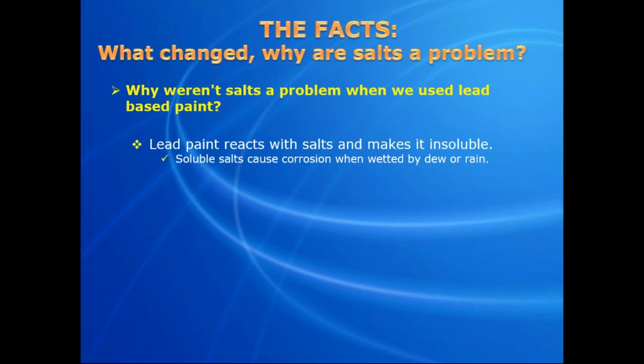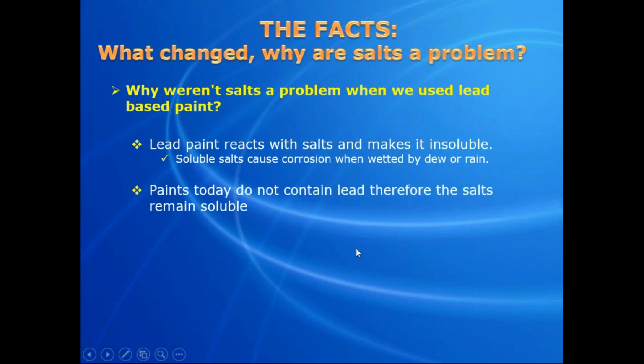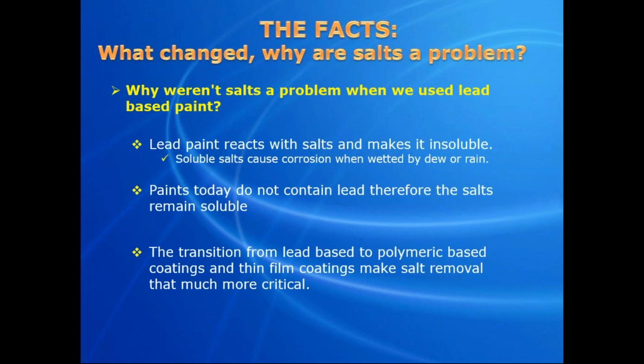Lead paints reacted with soluble salts to make them insoluble, as you see on the screen. Soluble salts without the lead cause corrosion when wetted by dew or rain. Paints today do not contain lead, therefore the salts remain soluble. The transition from lead-based to polymeric-based coatings and thin film coatings makes salt removal that much more critical.